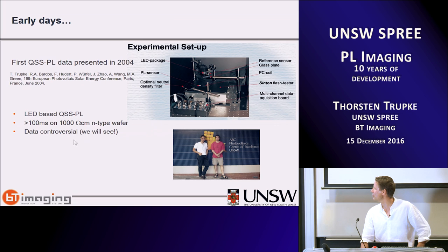We used it on very high-quality 1,000 ohm-centimeter n-type wafers, and we were able to show that these wafers had lifetimes exceeding 100 milliseconds, the highest lifetime ever reported up to now, actually. This data was reported in this conference paper in Paris in 2004. The data are still somewhat controversial because some people don't believe that a 100 millisecond lifetime is actually realistic. We do still have some of these wafers, and we're now in the process of applying modern passivation techniques to see if we can replicate those measurements from 2004. So we will see whether these data are real or not.